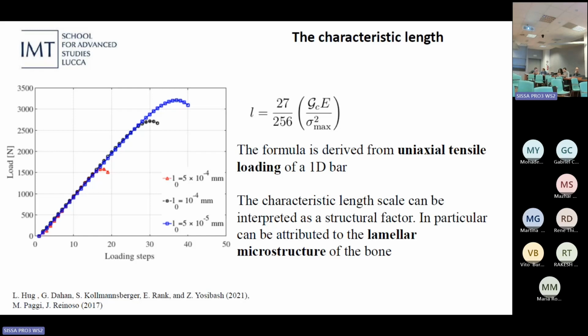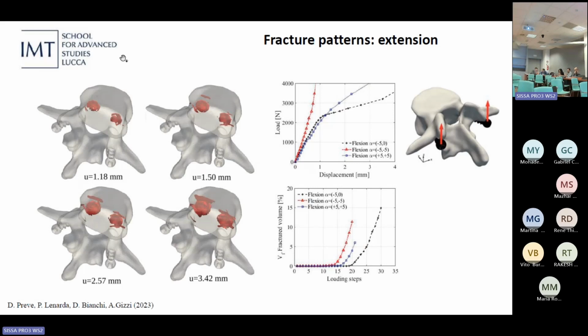This is interesting to know, because that value, which has been identified in the end of the day, has a dimension which is similar to the lamellar length of the bone structure. So it's very close to this value here, which is interesting because the crack initiation happens at the lamellar structure, at the microstructure, basically.